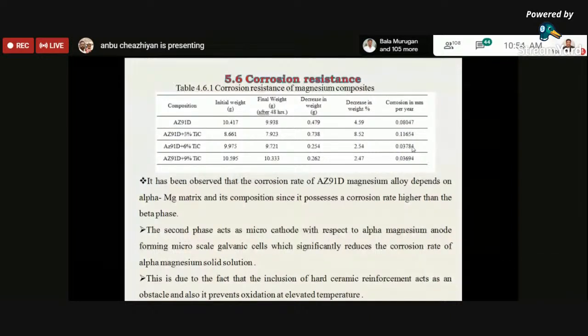So that is Mg17Al12 and Mg2Si. The second phase acts as a micro cathode with respect to the alpha magnesium anode, forming a microscale galvanic cell, which reduces the corrosion rate of the alpha magnesium. This is due to the fact that the inclusion of hard ceramic acts as an obstacle, and it prevents oxidation. That is a major reason for improving the corrosion resistance.